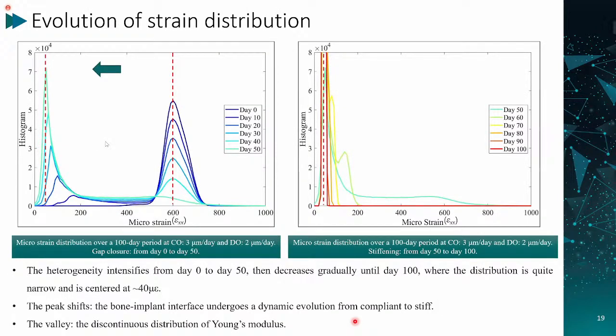So the heterogeneity intensifies from day 0 to day 50, then decreases gradually until day 100, where the distribution is quite narrow and is centered at roughly 40 microstrain here. So at day 0, you can see it's more general, but after that, when the healing process starts, the heterogeneity intensifies. This peak shifts from the 600 microstrain to the 40 microstrain, which means the bone implant interface undergoes a dynamic evolution from compliant to stiff.